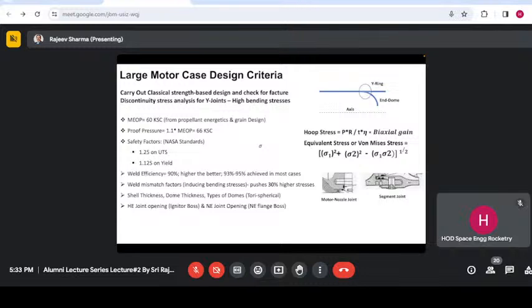So basically, you can ignore the third state of stress, which is the pressure, compared to the amount of stress, which is the longitudinal stress and the hoop stress. Which is why in a large cylindrical thin shell, it is called a biaxial state of stress. And because of the biaxial state of stress, the actual UTS, the ultimate tensile strength, is not the real strength. You get about 12% gain in the tensile strength.